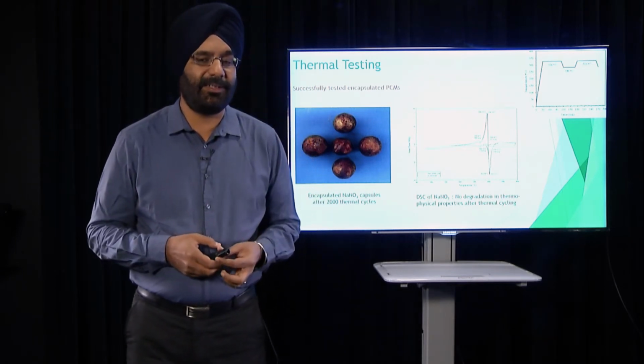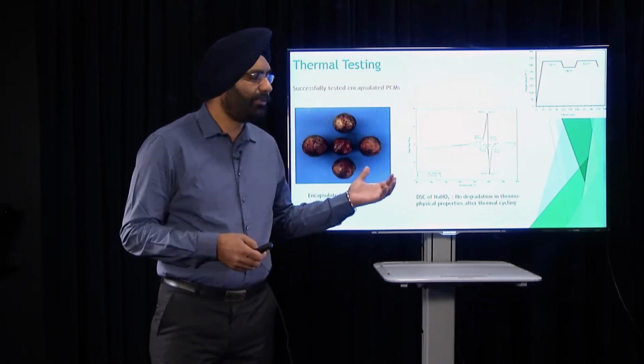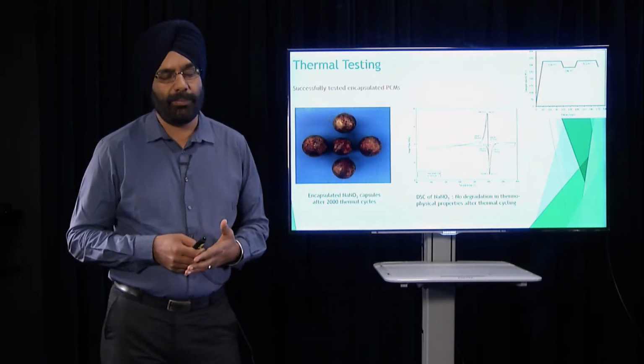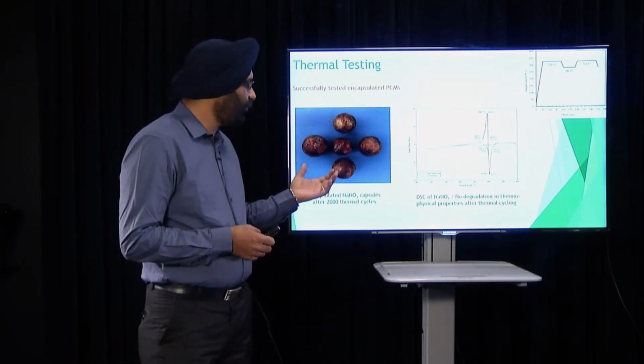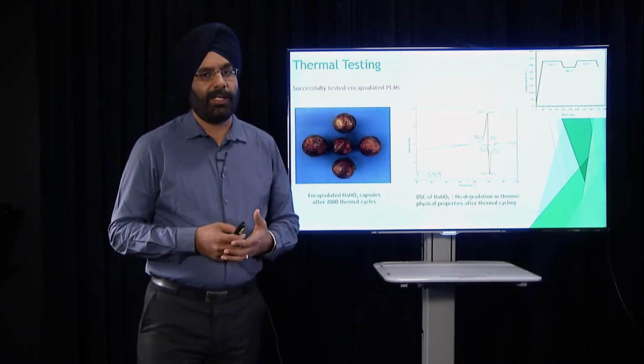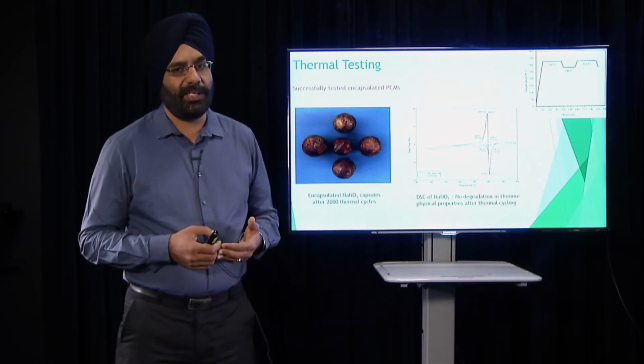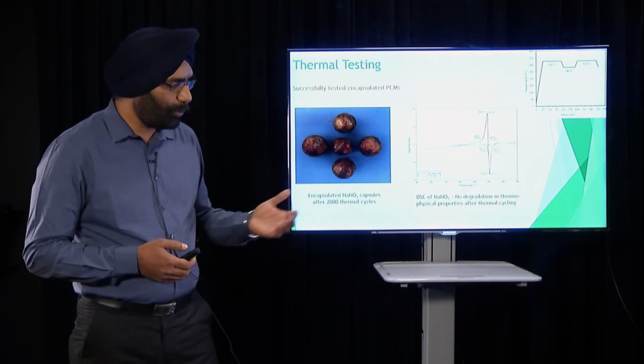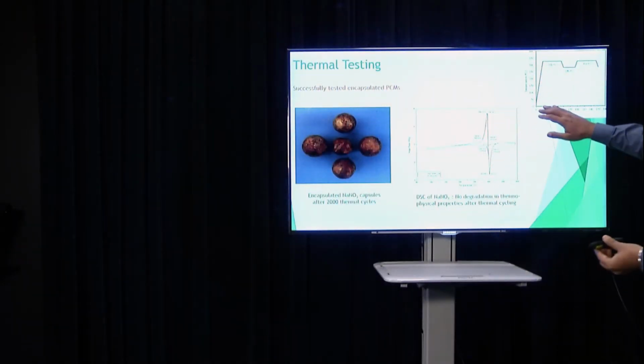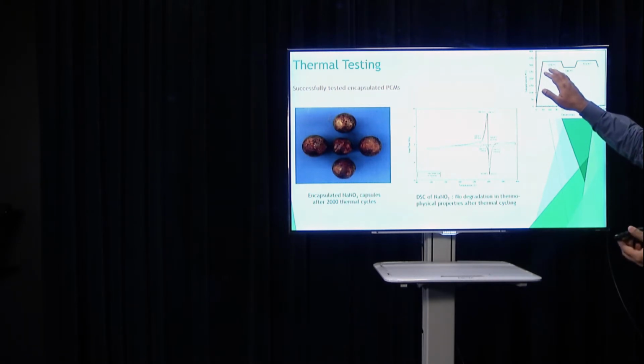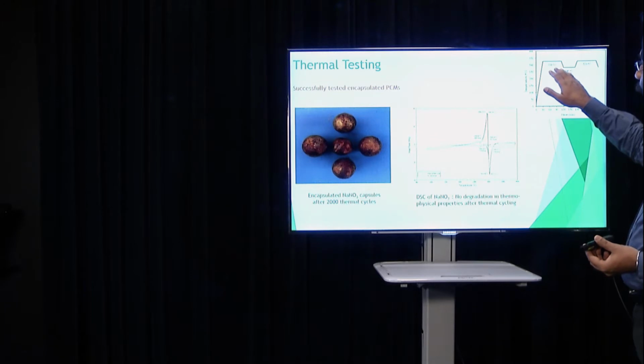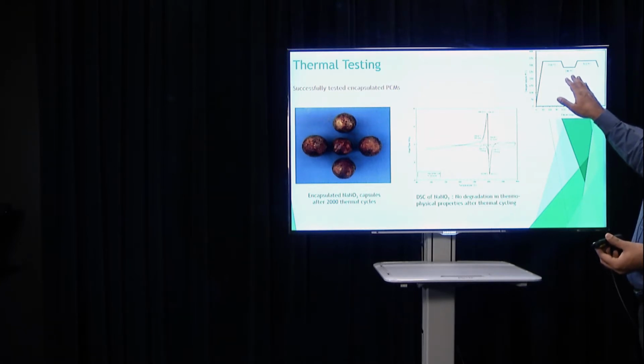So you need to do certain accelerated testing to see how these capsules survive the harsh environment of an energy storage system. So what we did is we made a number of capsules and tested them at very high temperature, like 326 degrees C. So in the testing, the capsules were heated to 326 degrees C, and kept at 326 degrees C for around 80 minutes, and then allowed to cool to a certain temperature, which is 280 degrees C. They were kept at 280 degrees C for 40 minutes to make sure that all the liquid inside got converted into a solid.